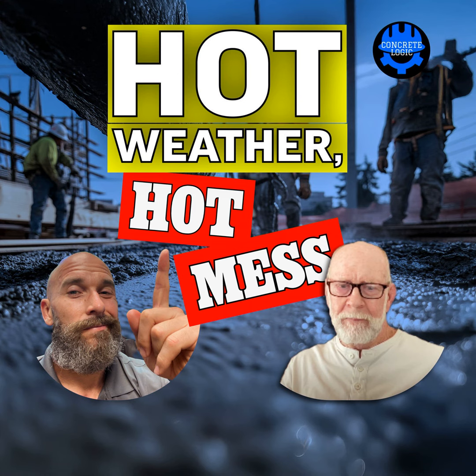Because they were showing, and that's the other one that frustrated me. In 3 different studies, I read how they put the water on the concrete surface, but it's not penetrating. They said because the concrete is so dense, it's waterproof, so it's not allowing the water to get in. I disagree with that completely. What happens if it gets really, really alkaline, it doesn't exchange very readily. And once it gets very alkaline, it also reduces relative humidity. The presence of water isn't as important as the relative humidity at the curing stage.